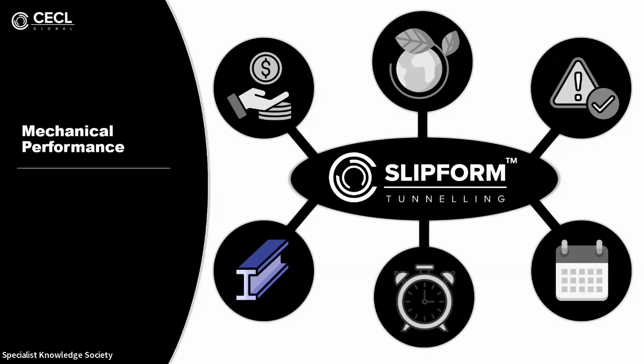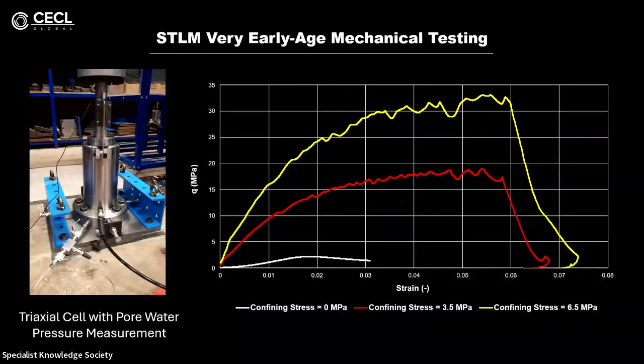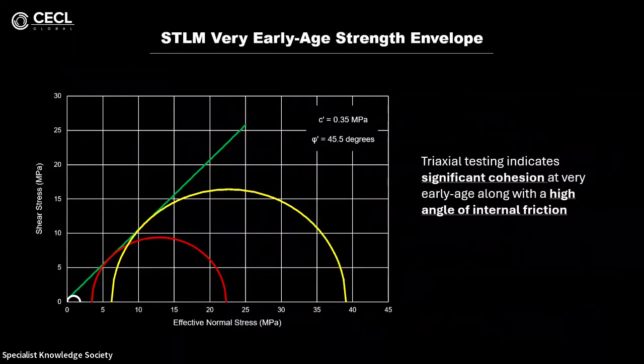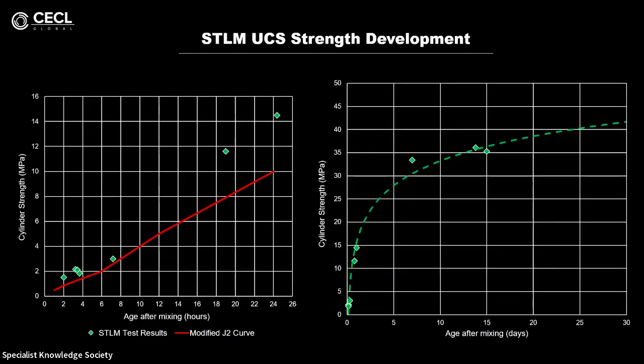So on to looking at the mechanical performance that we've observed in the testing. So the material exhibits a stress-dependent shear strength behavior from the triaxial testing that we've done in the very early age. This is also sub 2 hours after water hits the cement, as well as stress-dependent stiffness and ductile behavior as well in this material. So this can be fitted to the well-known Mohr-Coulomb relationship and strength envelope, where we've been able to demonstrate a significant cohesion to this material, as well as a high internal angle of friction for the material at very early age.